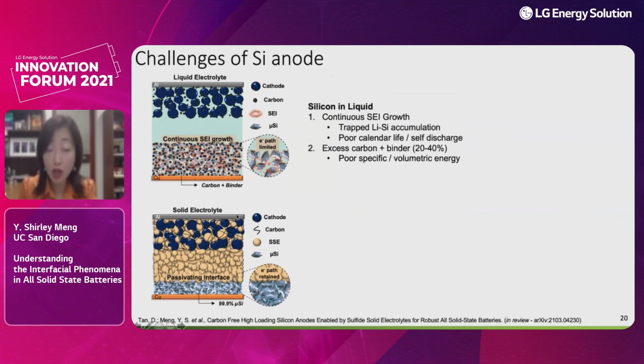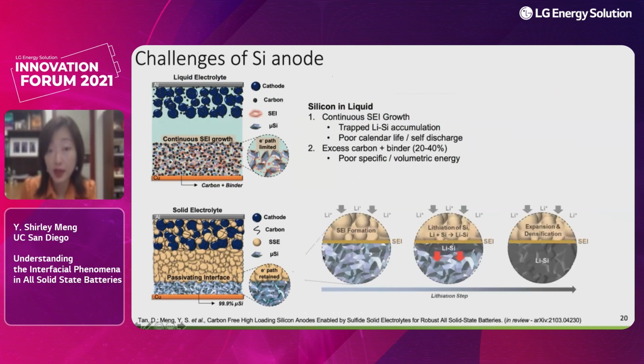In the solid electrolyte, the first important thing is we want to explore if the silicon can form a stable layer with the solid electrolyte. If it can form, since there is no solid electrolyte inside the silicon anode, this interface will be largely two-dimensional, and then we can rely on the good diffusivity of lithium in the lithium silicon alloys.